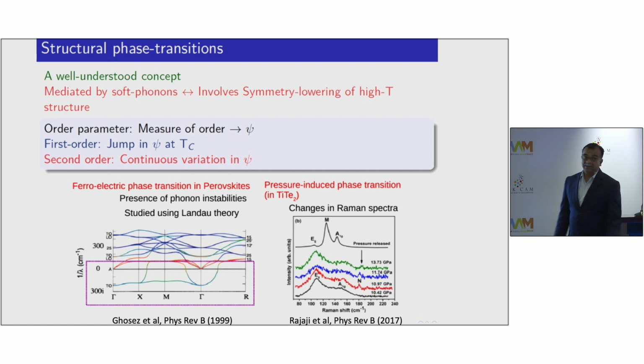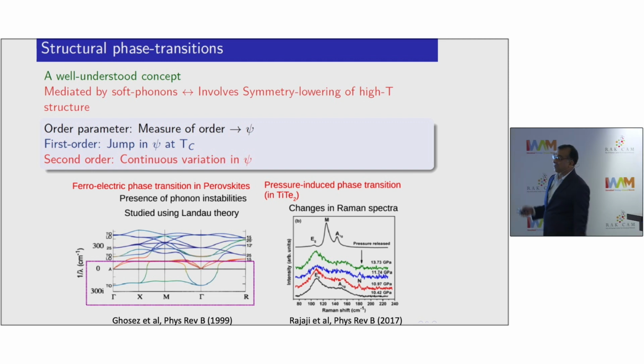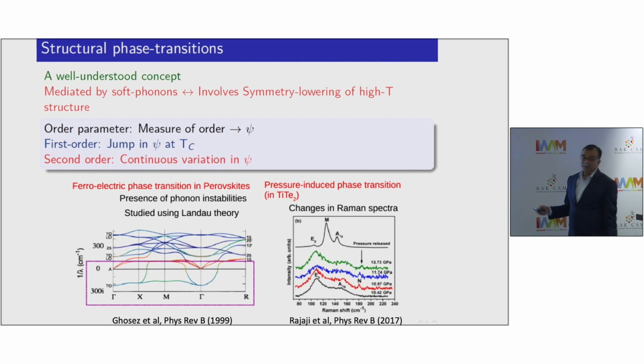So structural phase transition, the second idea, is a fairly well understood concept, mediated by soft phonons, which involve symmetry lowering of the high temperature phase. That phonon displacement basically constitutes the order parameter, or the measure of ordering in the low temperature symmetry-broken state. And they can be first order or second order phase transitions.